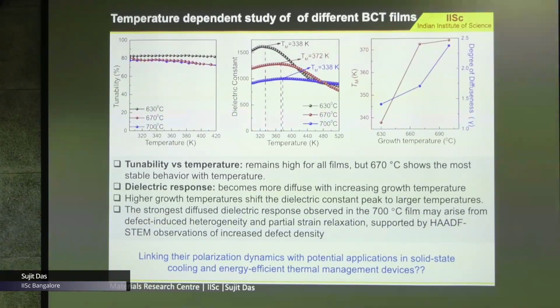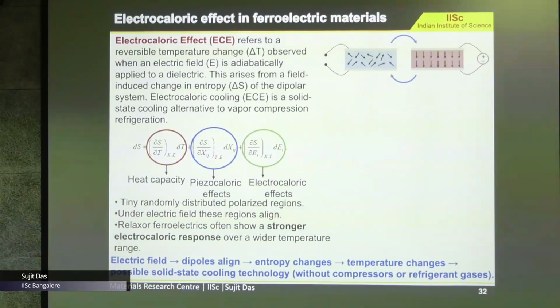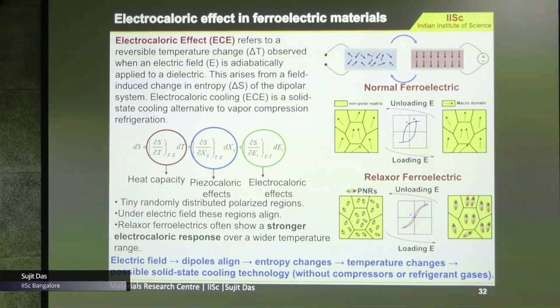So can we link their polarization dynamics with potential applications like solid-state cooling or energy-efficient thermal management? For that we measure the electrocaloric effect, which is basically the reversible temperature change observed when we apply the electric field adiabatically. What generally happens in ferroelectrics is, if you apply the electric field, the polarization is basically aligned, and if you take out the field, they have a hysteresis.